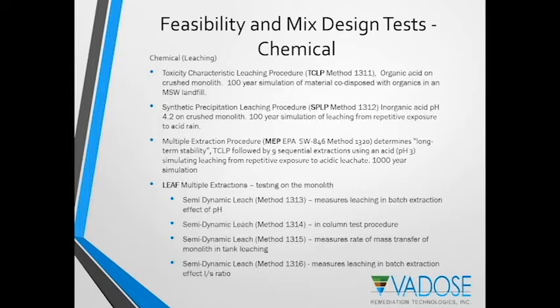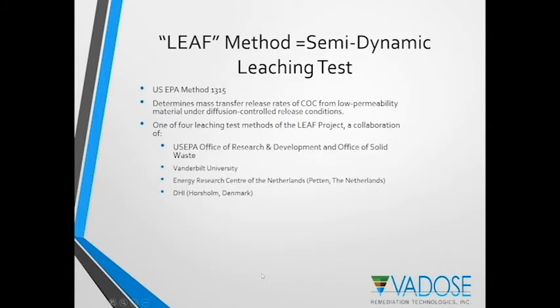Method 1314 is similar in nature, however, it's done in a column test. Method 1315 is used to measure the rate of mass transfer from the monolith in a tank leaching experiment. So again, in this case, you're measuring the rate at which contaminants are migrating from this monolith. And then finally, method 1316 is measuring leaching in a batch extraction method as it's affected by the liquid-solid ratio. So essentially, depending upon how much liquid there is in relationship to the solid, how does that affect leaching of these contaminants?